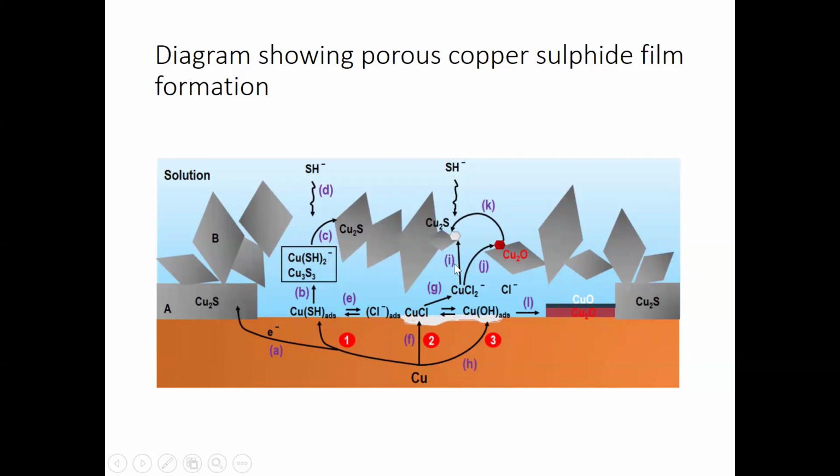Importantly, you can still be having reactions occurring at the surface with other oxidation products. So if you had already present oxide built up on the surface from the previous corrosion steps that you expected in the DGR, so this would be, let's say, having oxic corrosion happening when you initially buried it, either under humid or saturated conditions, those corrosion products could potentially themselves be further corroded by sulfide. It kind of depends. From a modeling perspective, you shouldn't bet on that. You should bet that only your actual copper surface is going to be corroded.